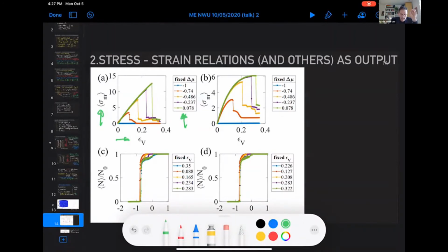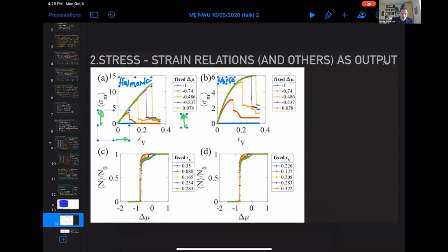On the left-hand side, you see a harmonic potential. So please note this is harmonic for the harmonic case, so basically linear elasticity. On the right-hand side, you have it for the Morse potential. So you can generate, if need be, these stress-strain relationships. But then there is another quantity shown at the bottom here, which is actually a bond isotherm. That's for those of you who worked on the problem of adsorption, chloride diffusion. You all know about this, but basically the idea is delta mu is the prescribed chemical potential, and on the y-axis, you have the number of remaining bonds, n over n0.